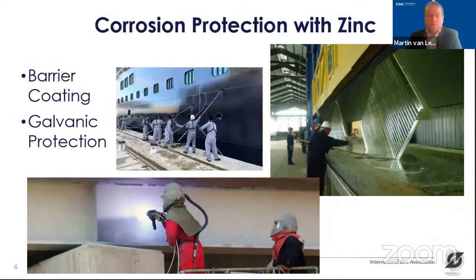So zinc coatings do not only provide a barrier coating, but they also provide a galvanic protection or sacrificial protection to the steel. You can see some pictures here of the various ways to apply zinc coatings. You can do it by painting of zinc-rich paint. You can do it by hot-dip galvanizing, which is the right picture, or in the bottom you see somebody with a spray gun applying thermal sprayed zinc coatings on a bridge.